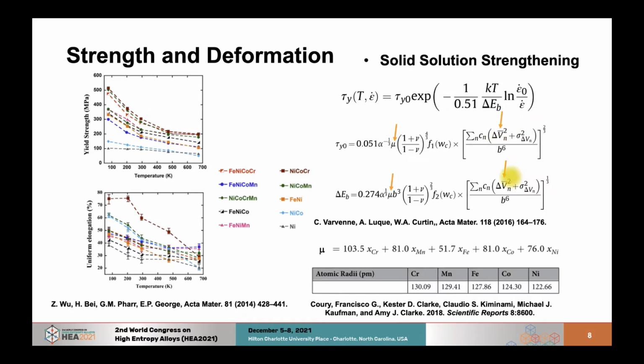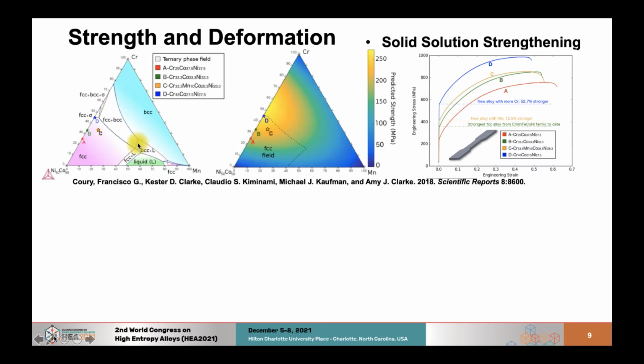And what we show here is that chrome is the element that apparently increases the shear modulus the most, but even more important, when we have chromium, that is the biggest atom in this system, and we mix it with cobalt and nickel, we get very large delta V here, which is the atomic volumetric mismatch. So this is better shown in this picture here. So here we have 50 nickel, 50 cobalt, and here we have chrome, and this end is manganese. But we're really interested in this line.